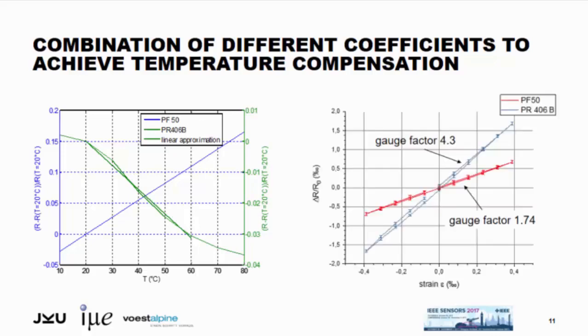We also characterized the gauge factor of those two structures, which you can see in the right plot. The gauge factor for carbon black was about 4.3, which is expected but could be a little bit better. But we're working on improving that. I think it's due to the manufacturing steps involved. While the gauge factor of silver is about 1.74, which is also expected because metals would not exceed 2 anyway.